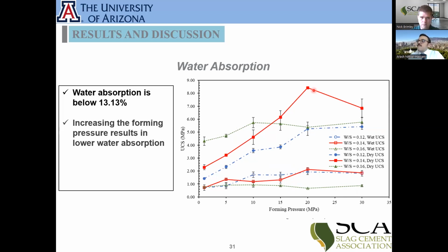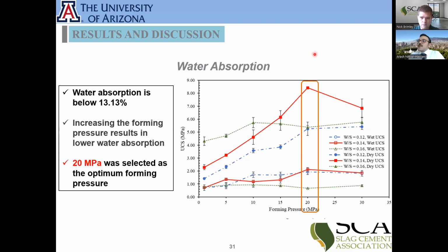And we noticed that the samples pressed with 20 megapascal forming pressure are giving us a more durable material with higher UCS. So we decided now that we are going to use 20 megapascal forming pressure, and the best sample is 14% water content. So those are the criteria we are going forward with. And why is this happening? Probably the combination of 14% water content and 20 megapascal is a favorable condition where we keep all the liquid in the system, and at the same time we are compacting the material enough to have a better microstructure.